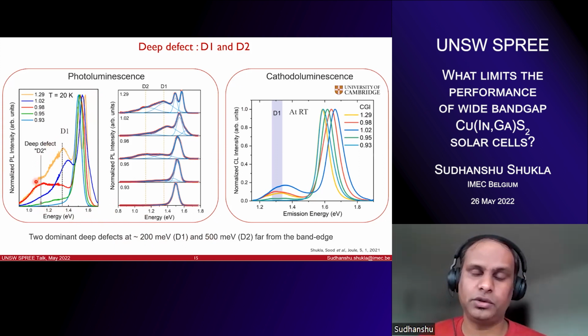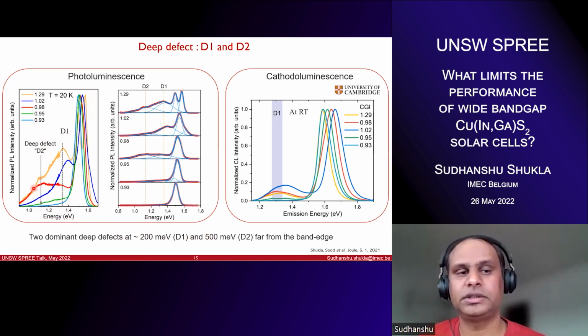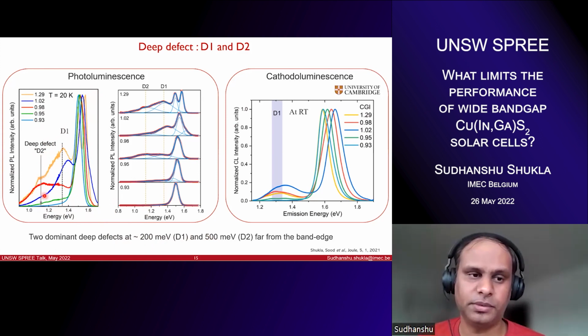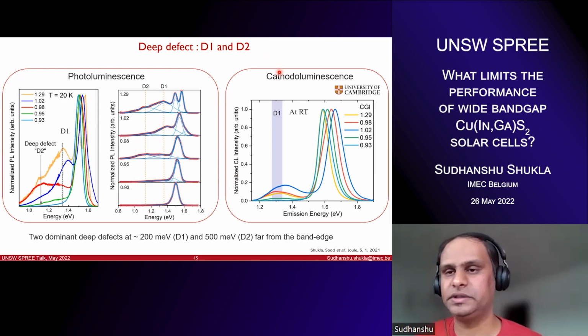One could imagine that your quasi-Fermi level splitting or the maximum voltage can never exceed this defect. Unless you passivate it, your VOCs are not going to be any better than 1 point something volts. Here also it shows the same thing, that if you reduce the copper content, you see these defect bands disappearing slowly, and the D1 band remains a bit. So if you plot it in the log scale, you still see some intensity of the D1, but the D2 actually suppresses quite substantially.